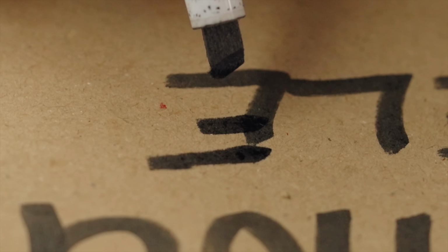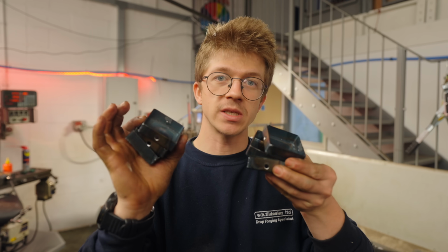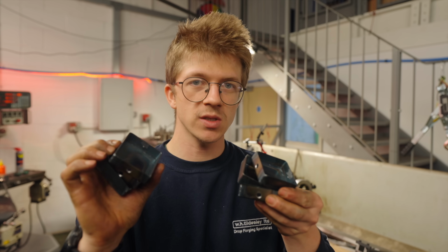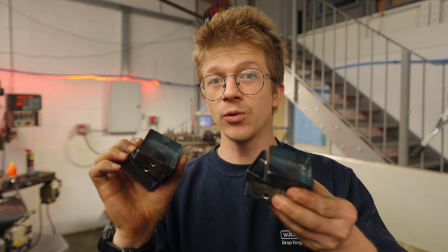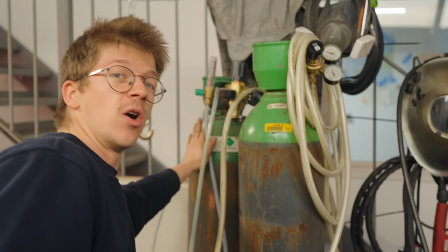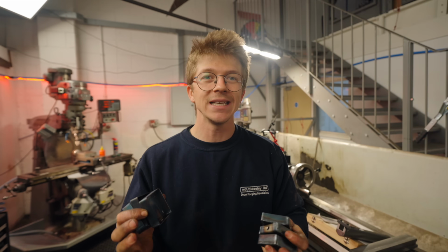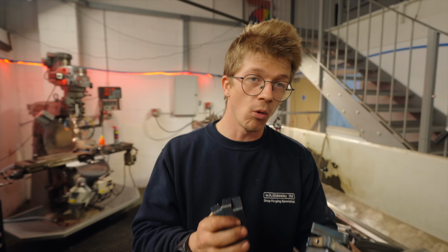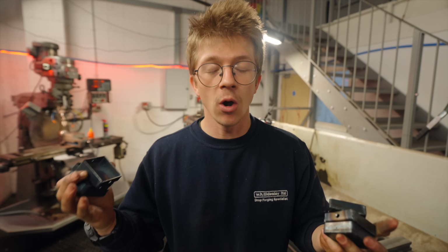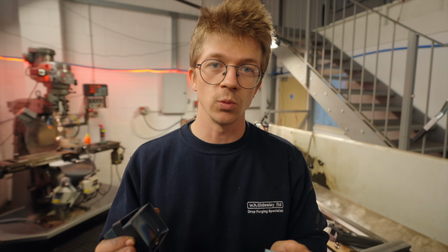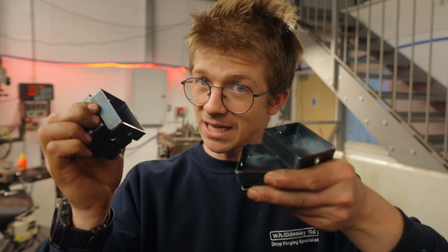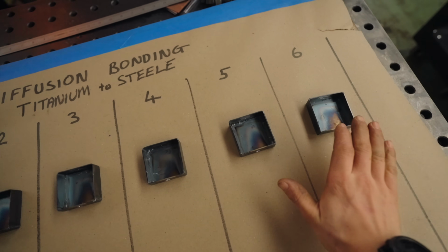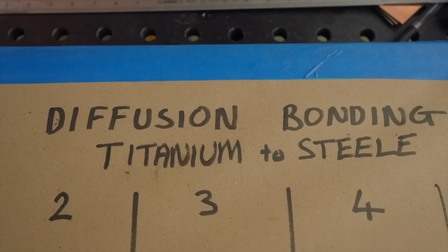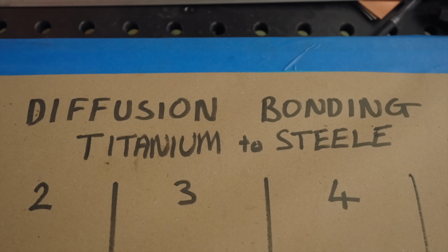I accidentally put an E on the end of steel. I've made up all of these boxes so that once we put our steel and titanium in, we can seal them up and pump inert argon gas through, so that at the high temperatures, neither the steel nor the titanium will react with the oxygen in the air, causing oxides that will stop them from sticking. I made 6 of them because we've got 6 experiments to run, but I think it's time for us to figure out what diffusion bonding is.